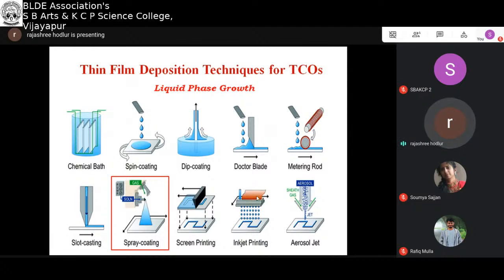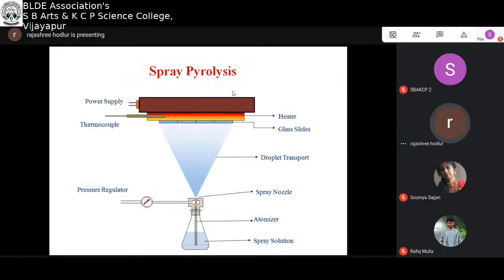My main focus further in this discussion will be on the spray pyrolysis technique, which is a very versatile liquid phase growth technique. So this is our home built setup, which we designed in our laboratory. This is the atomizer, this is the heater, and we have not used the conventional spray approach. This is the heater here, and the glass slides fitted here. So you can observe the atomizer with the precursor solution, and once it is sprayed on the preheated glass, one can obtain thin films of various types. So this is our home built spray pyrolysis setup.